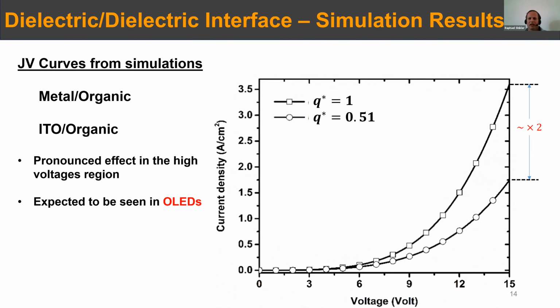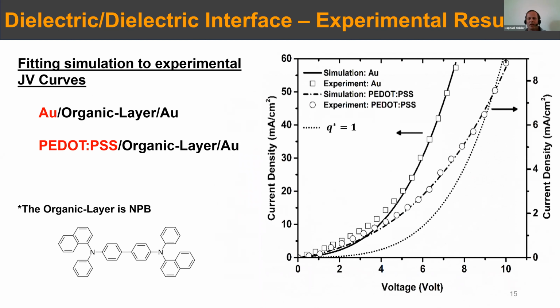And then we went and we didn't want to involve also 2 types of carriers inside, like we have in the solar cell, but we wanted to focus on just 1 type of carrier. So we introduce NPB between 2 metal layers of gold and between PEDOT:PSS and organic layer, the organic layer and the gold. And as you can see, there is a difference between the expected current and between these 2 types of contacts. And our results fit quite nicely, not on the low voltage regime, but when you go to voltage of around 3 volt and higher, then they fit quite nicely with the experiment.